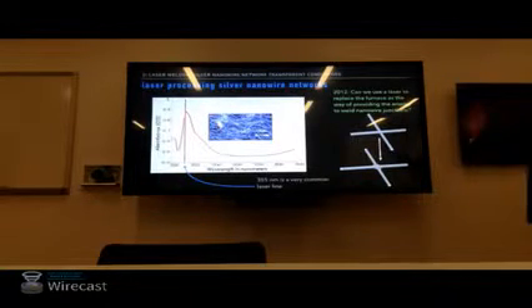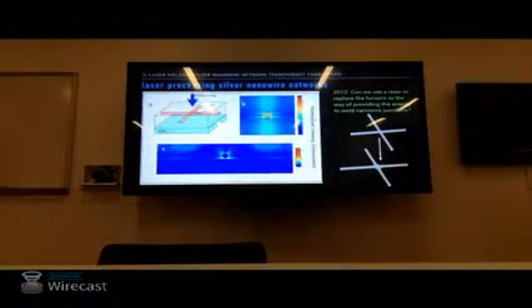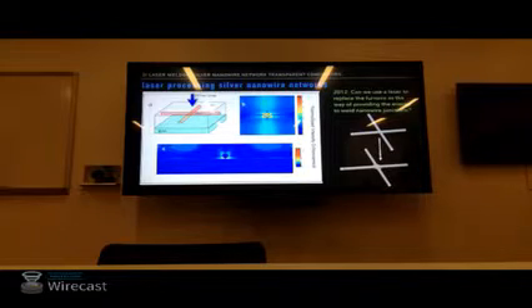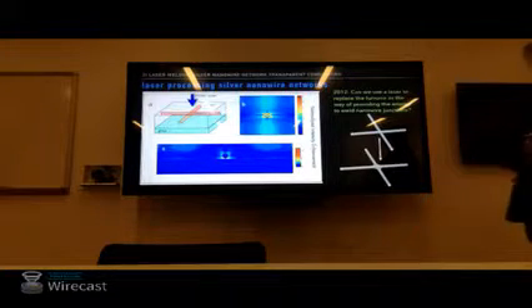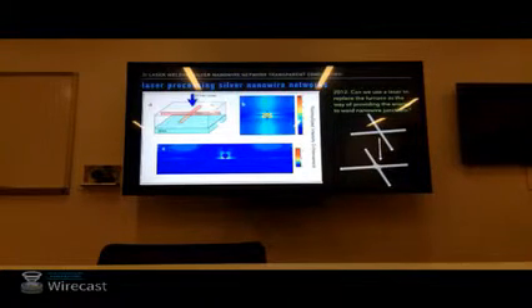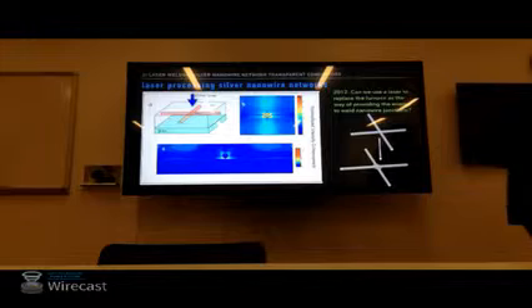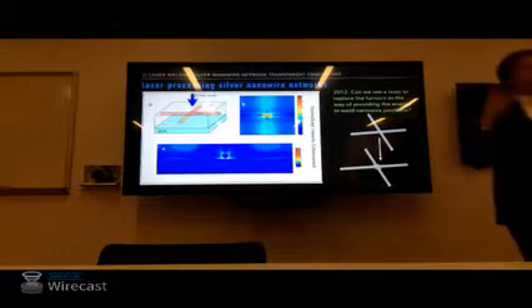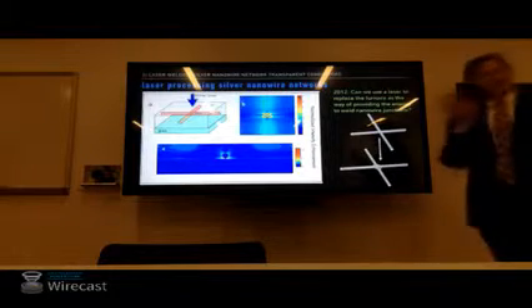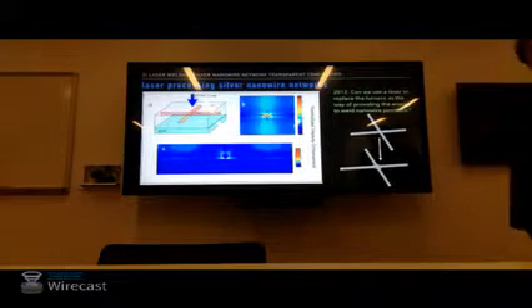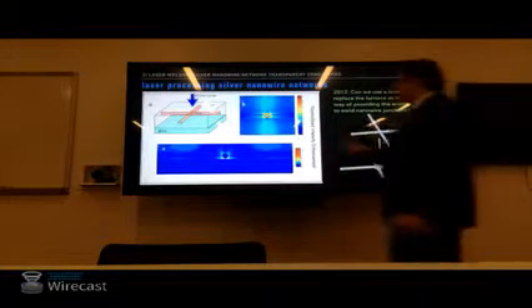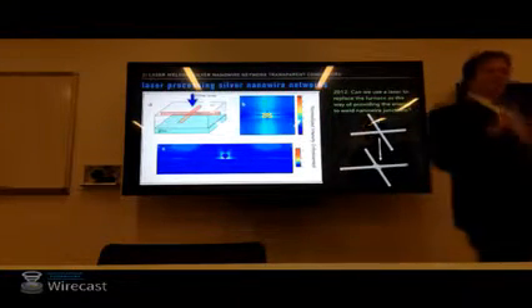We want to know, can we use this laser wavelength to do the process? And the first thing we can do is some optical simulations. So this is a finite difference time domain. It solves Maxwell's equations in a 3-dimensional space. So we define our materials, crossing silver cylinders on top of glass. We send in monochromatic light, and we keep propagating the waves until a steady state is reached. And we look at intensity enhancement. So if we had uniform intensity in, we look at where that intensity ended up. Do any of these structures act like antennas? And what we see is precisely at the junction between nanowires, we get an intensity enhancement.